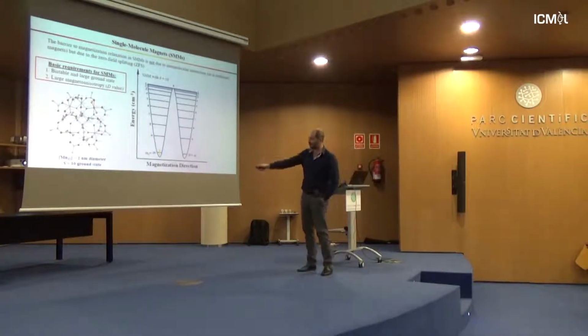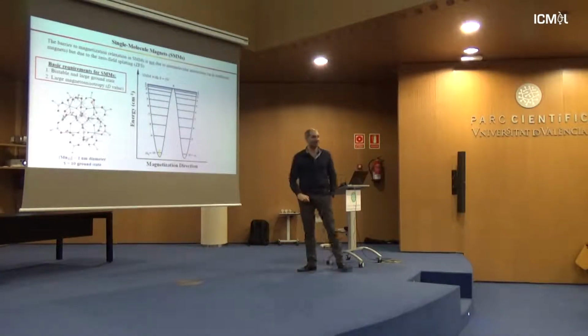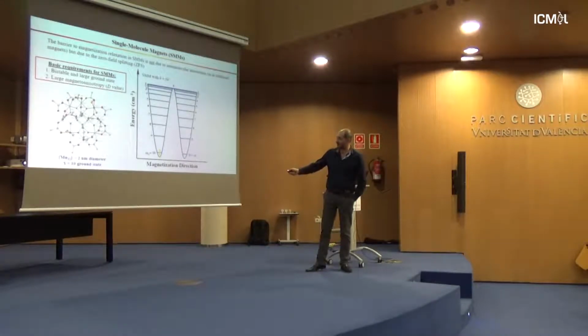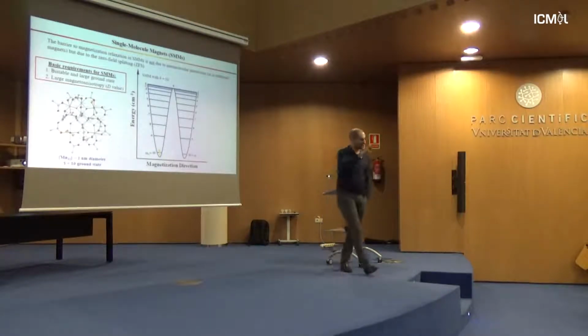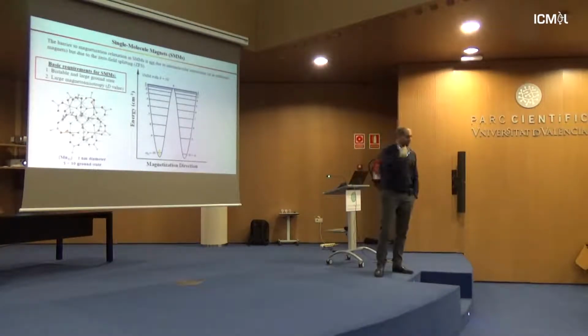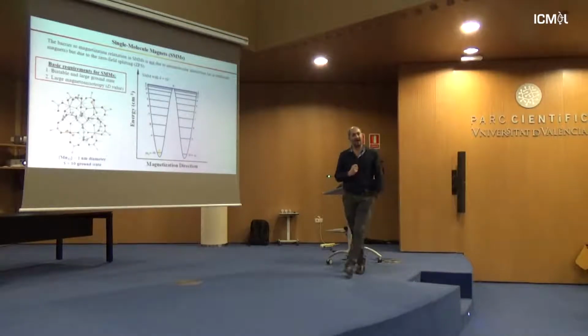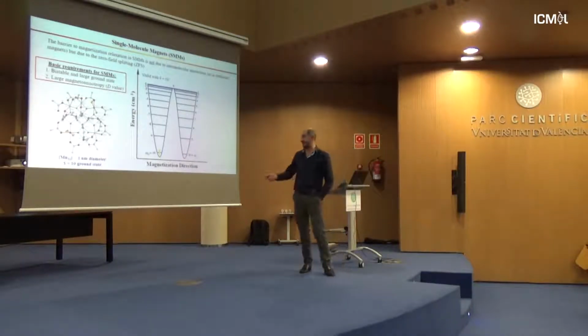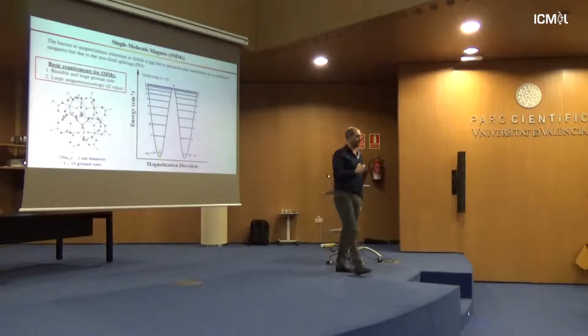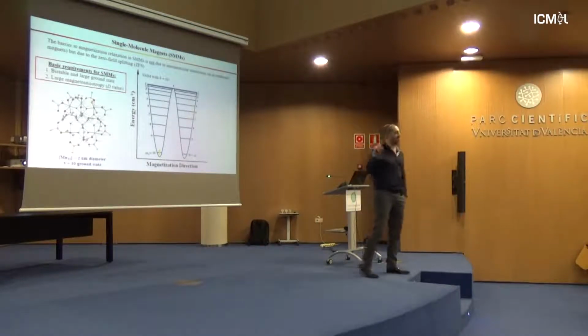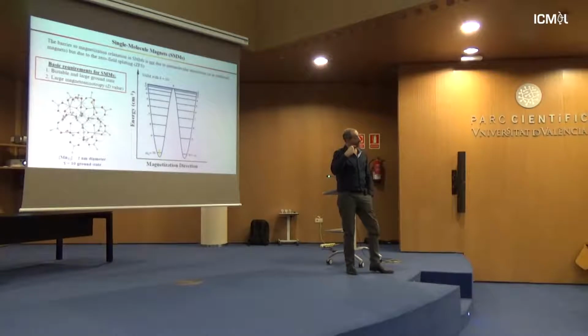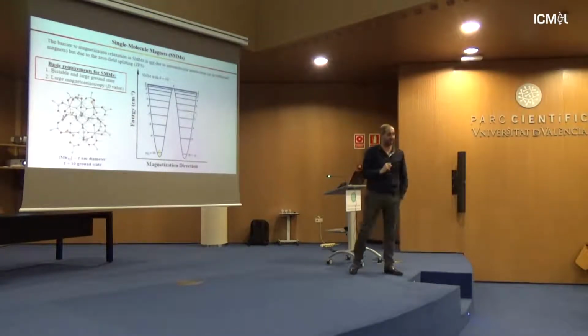The outer domain, or the outer ring of manganese 3+ ions, which are ferromagnetically coupled, and the ferromagnetically coupled cubane here, but these interactions are antiferromagnetic, so the overall compound can be described as ferrimagnetic, with the S equal to 10 spin ground state. It's a large, but not the maximum for this system. So lots of people started thinking why this compound has an S which is not the maximum one.